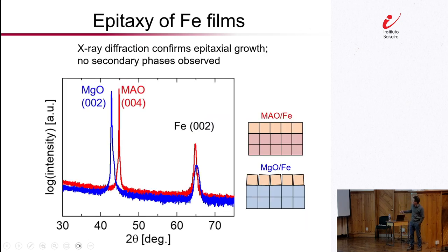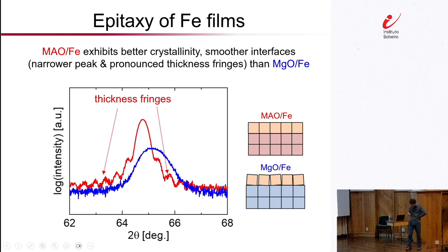And we can, of course, directly compare the crystalline qualities of these two types of samples through X-ray diffraction. Okay, so here, what we see is quite promising. We only see a diffraction peak from the substrate and from the film itself. No other phases. So it appears to be a nice single phase crystalline sample. But we can say a little bit more by comparing the diffraction peak corresponding to the film plane. So one thing you immediately notice is that the sample of iron on MAO has a much taller and sharper diffraction peak. And moreover, we also see this series of oscillation peaks, what we call thickness fringes.